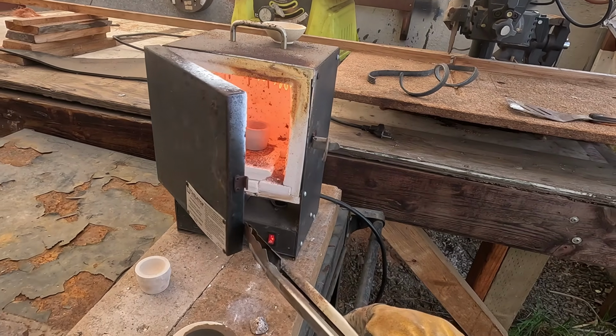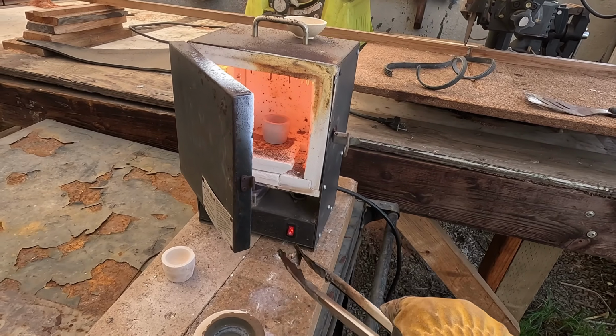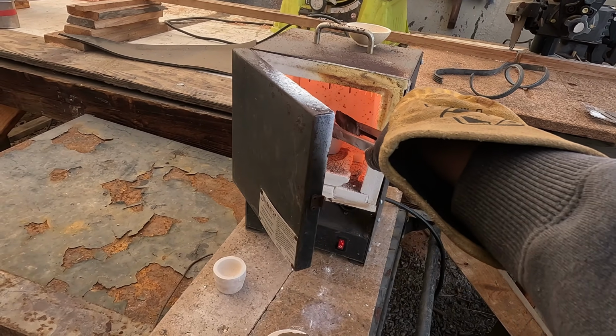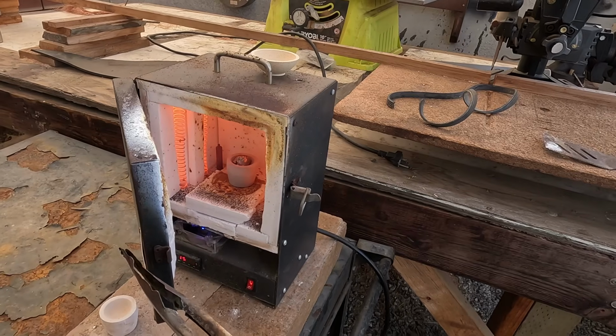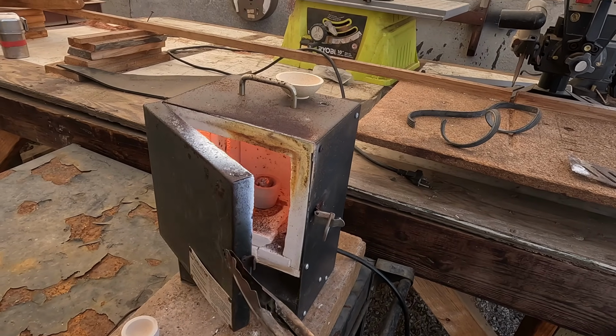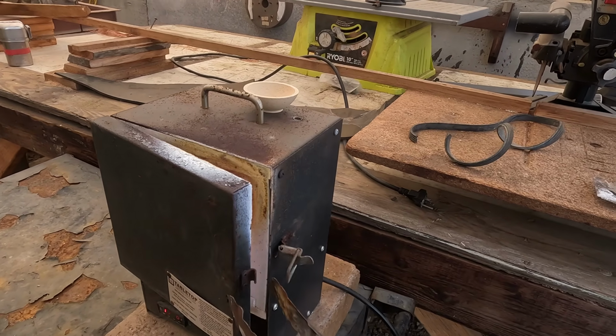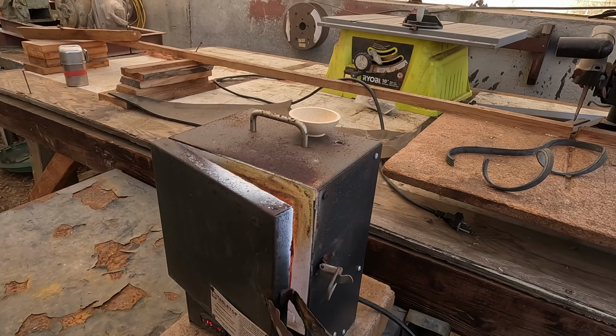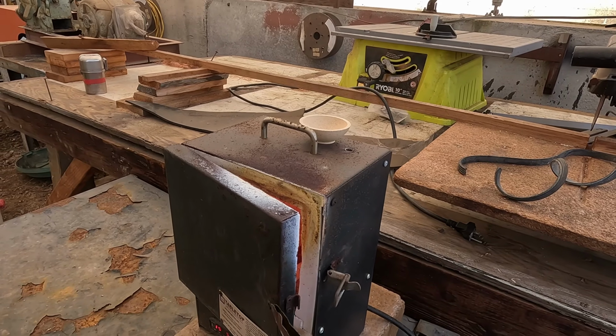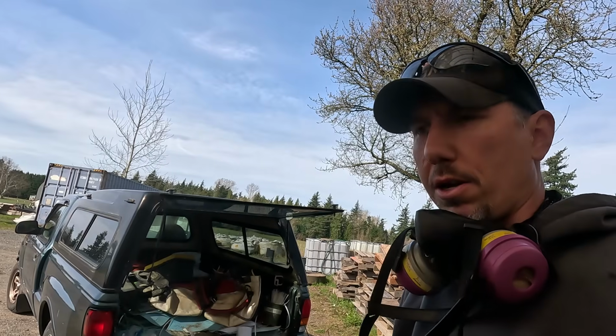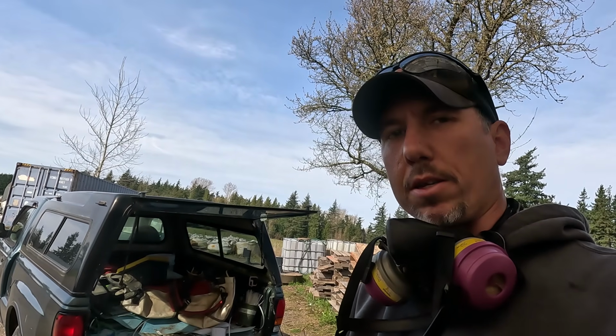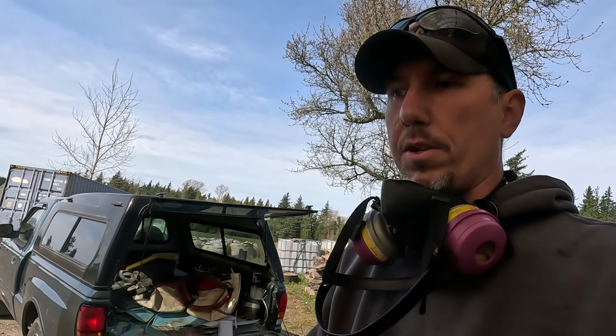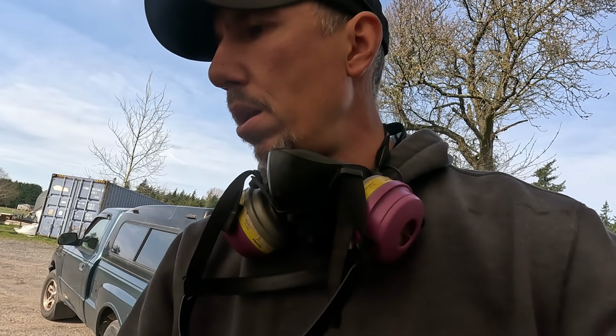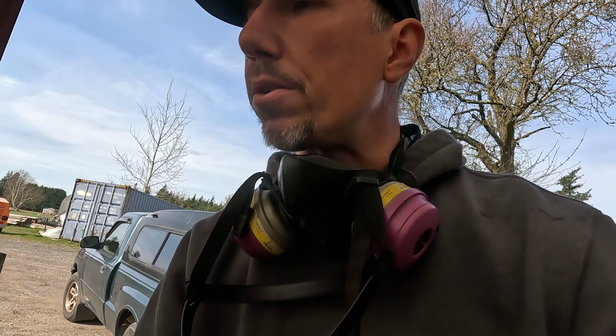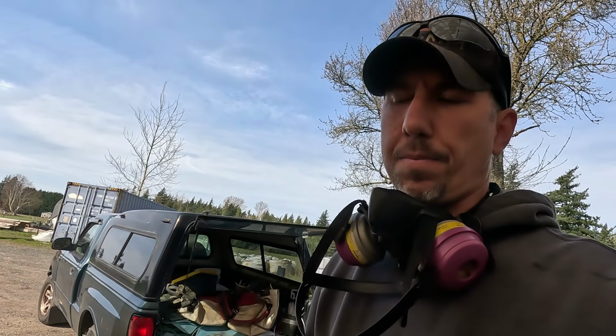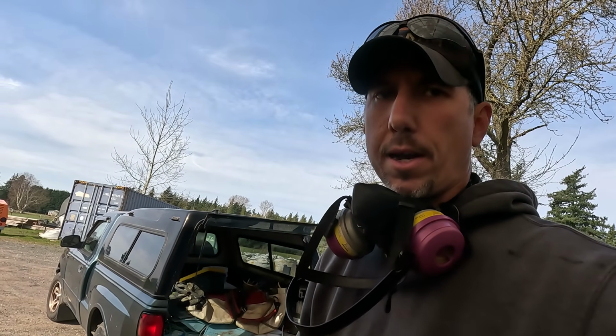All right, here we go. Preheated cupel. There's our 40 grams. That cupel should hold about 60 grams worth. So my hope is that if I have to add a little bit of bismuth later, then we can still absorb all those oxides. I'm gonna watch this for a second here because I should be able to tell if it's mostly copper by how fast it melts. So we'll keep an eye on this, but